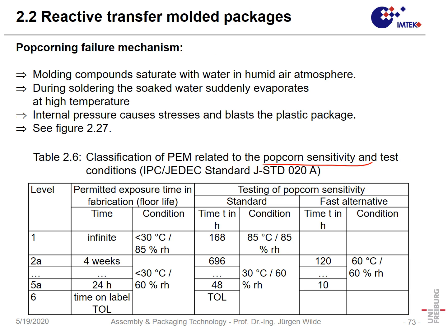So if you keep it overnight and for more than 24 hours, and you have only popcorn sensitivity level 5A, you could expect that later on you will have popcorn effects. The worst case is if it's below 24 hours and if only a certain time is given on the label.